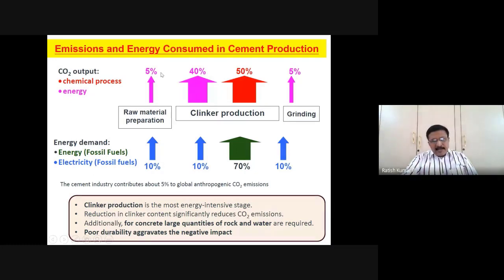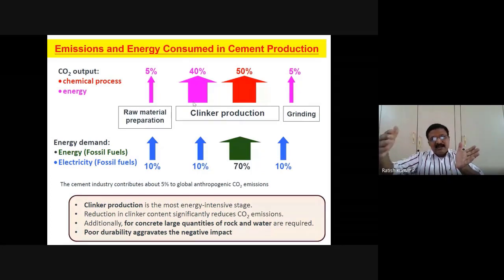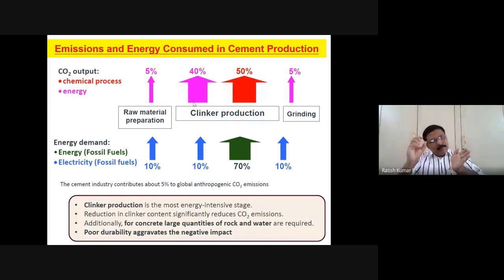As you can notice here, the pink part which I'm showing you is the carbon dioxide output in terms of energy. When you burn at 850 to 1300 degrees centigrade to get the requisite products like alite and belite, which are very important from the strength point of view, and B-lite also from the durability point of view, you expend a good amount of energy. At the same time, the chemical process also releases a good 50% of the emissions. So out of the 100% emissions, 50% is from the point of view of energy, be it fossil fuels.